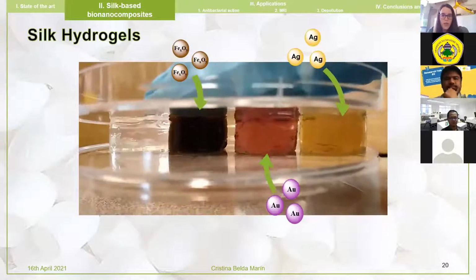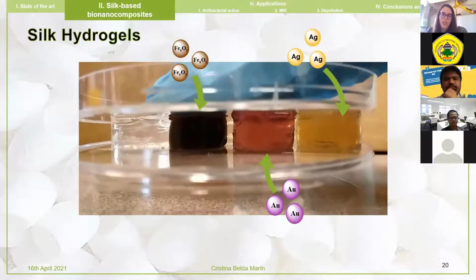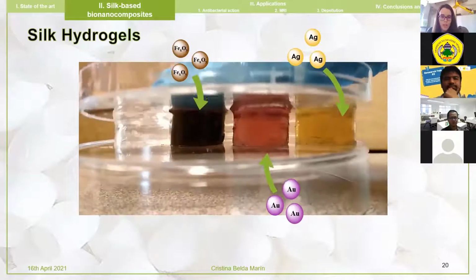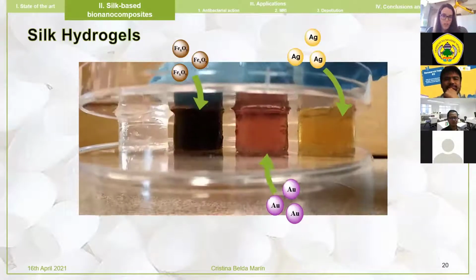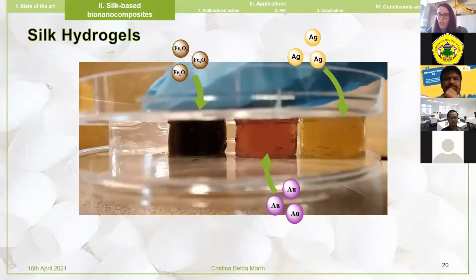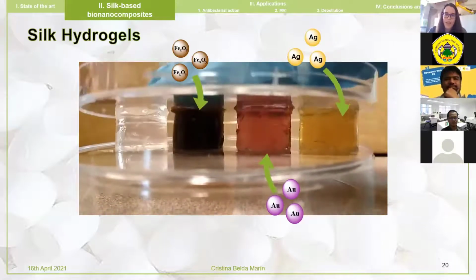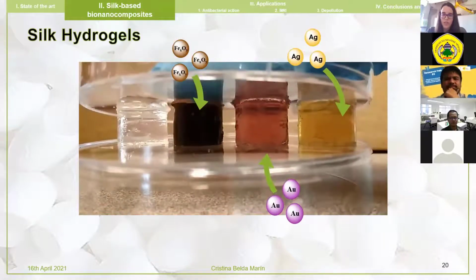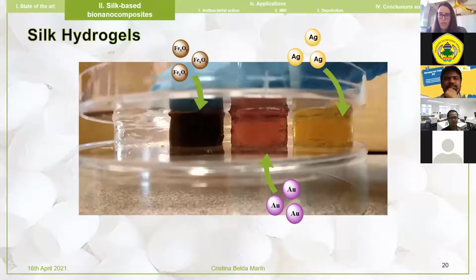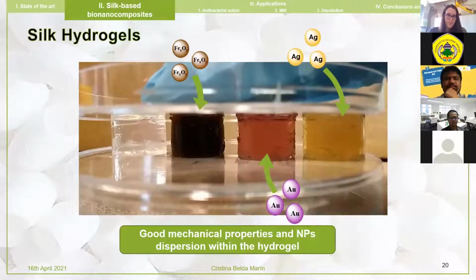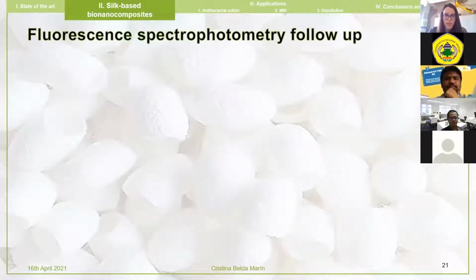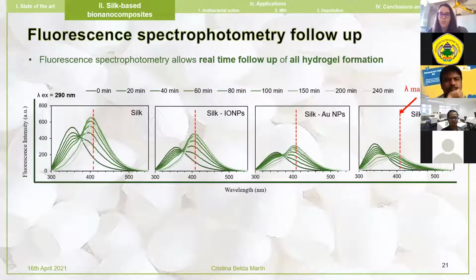And here you can see what the different hydrogels containing nanoparticles look like. So transparent is silk hydrogel alone, and then you have iron oxide, gold, and silver. And as you can see, they are quite strong, as you can push them and they do not break. So we checked whether the fluorescence follow-up was possible in presence of the nanoparticles, and we were surprised because it is possible, but we have a lower intensity.